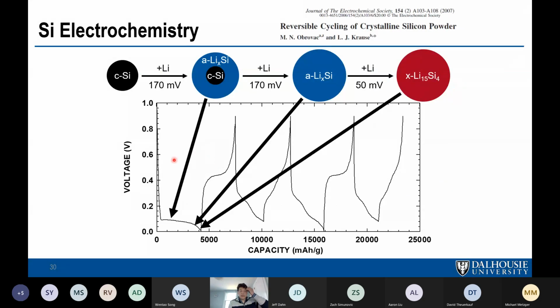So with these results, we can get a picture of how silicon is being lithiated. You start with crystalline silicon, and you lithiate in a two-phase region. And that means the lithium is coming from the surface, so the second phase of amorphous lithiated silicon is forming on the surface. And it grows at the cost of the crystalline silicon in the core until the whole thing turns to amorphous lithiated silicon. And then when the voltage starts going down to 50 millivolts, it suddenly crystallizes into this 15-4 phase.